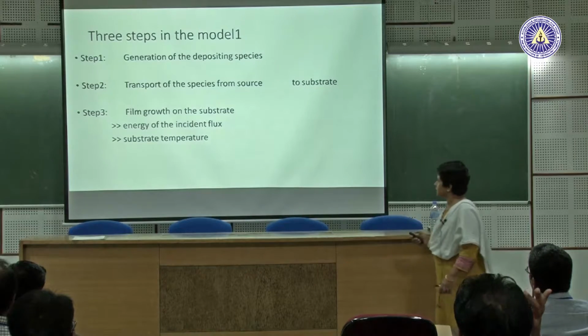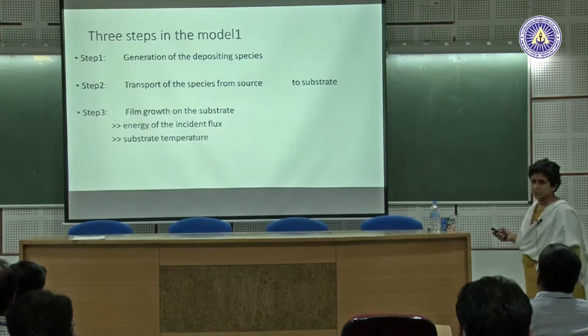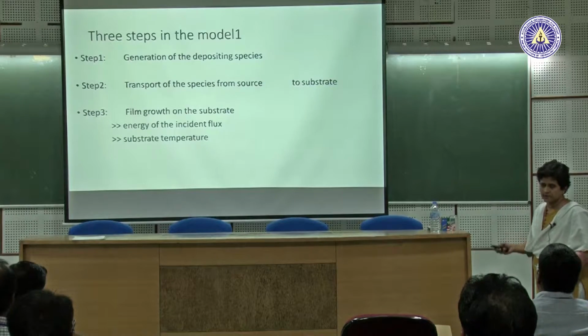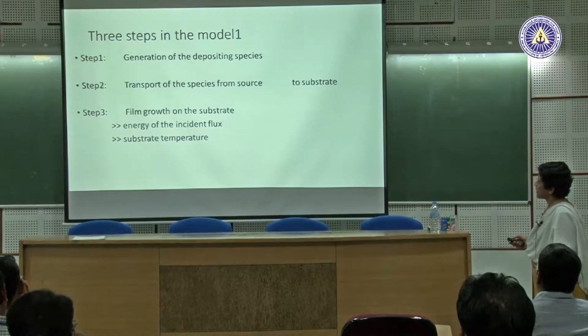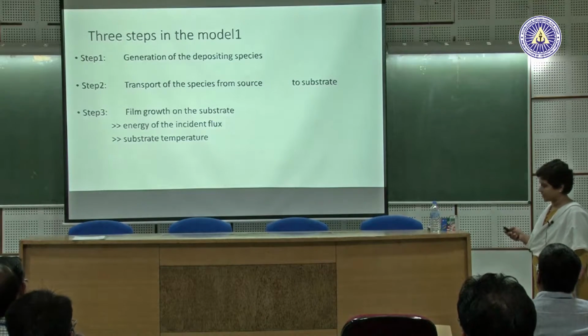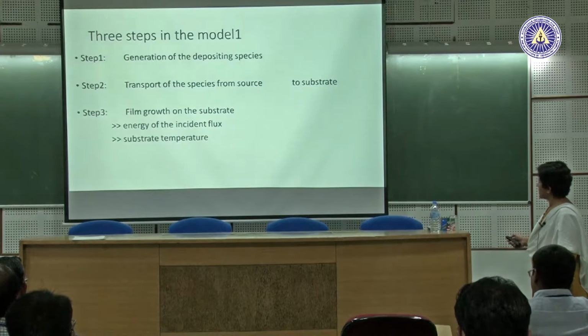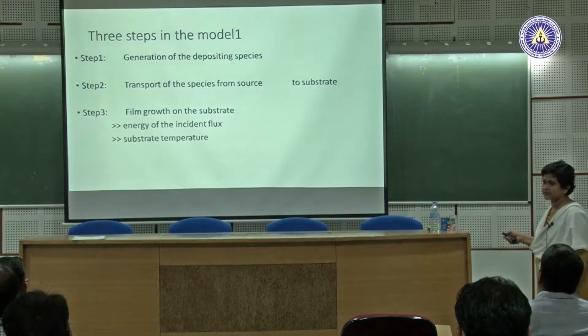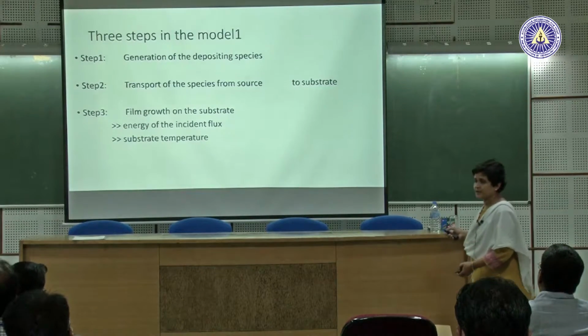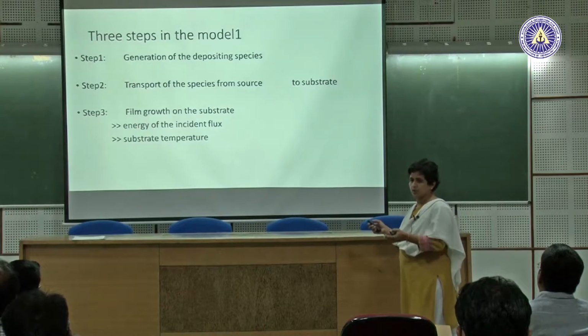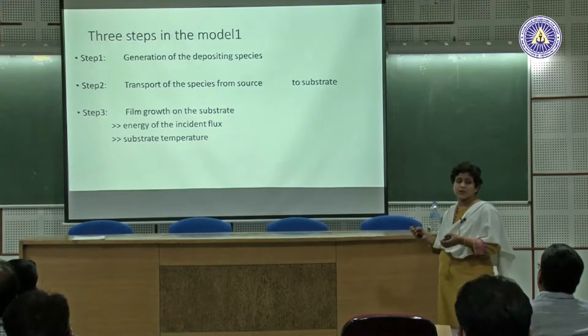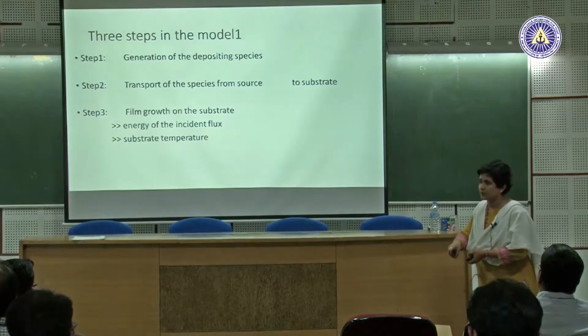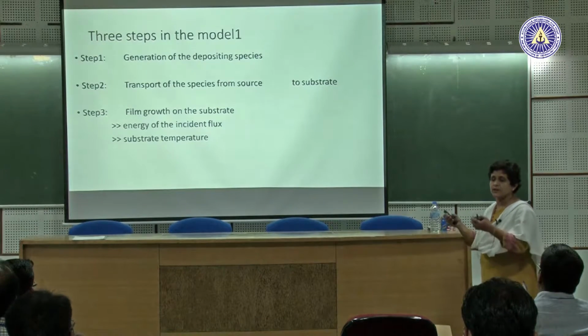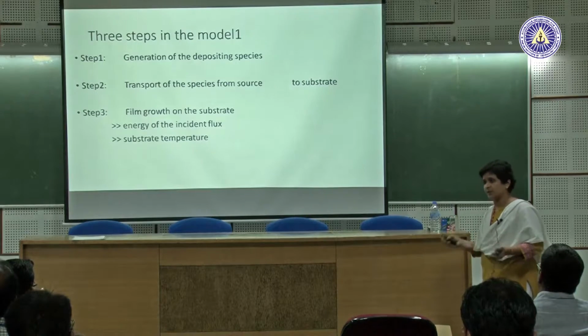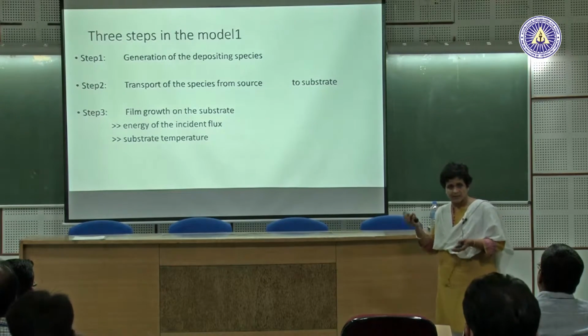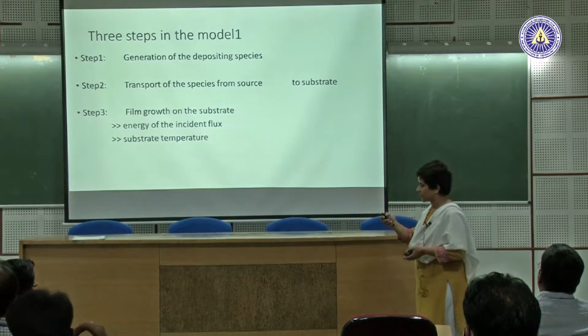So, there are 3 steps to the evaporation. The first step is generation of the depositing species, which can be just heating the material, thermal evaporation, or E-beam evaporation, or laser evaporation. So, depending on how you generate this material, each technique gets a name, right? So, if you were heating just thermally by some coils or something, it's thermal evaporation. If you are heating the material by shining an electron beam on it, it becomes E-beam evaporation. If you are heating the material by shining laser beam on it, it becomes laser deposition. So, how you create that species which will form the film will decide a particular technique.